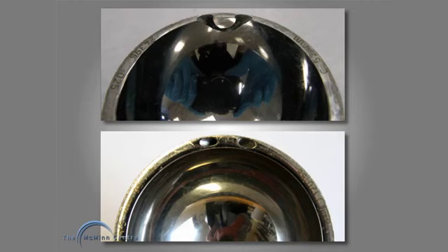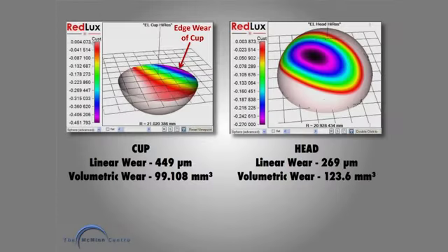This is a BHR that has been inserted with a high inclination angle, and you can see that the wear on the edge of this implant has gone right into the wormhole. These wormholes are in the edge of the cup to hold the introducer cables, and on the bottom photograph that's what it should look like. So there's a serious amount of wear with this high inclination angle implant. Usually the wear is not so dramatic as that, and you have to use one of a few different methods.